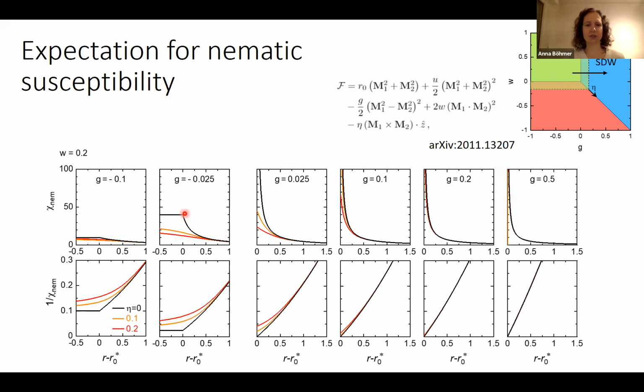It doesn't diverge. And once we add a field eta, it gets suppressed and the transition is washed out. If we are deep in the stripe phase, the eta field has basically no effect at all. In this intermediate one, it suppresses the transition. We go from a divergent nematic susceptibility to a non-divergent one. And the ground state changes from stripe to spin vortex crystal.